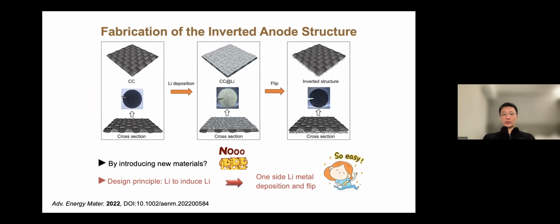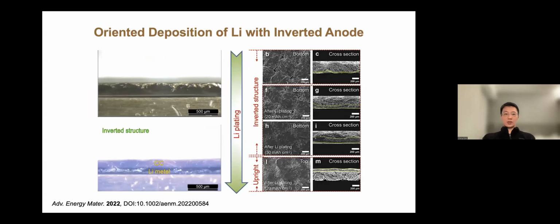So this experiment was very easy. You just do the same thing that I showed you in the Nature Communications paper, and just flip it around and then assemble the cell. What you observe is, in this inverted structure at the bottom, we don't really see lithium metal deposition and form dendrites. You do see an expansion of lithium metal, very little, and that's normal. But on the upright structure, which is the normal one, you do see a huge amount of dendrite formation in a very, very short period of time.